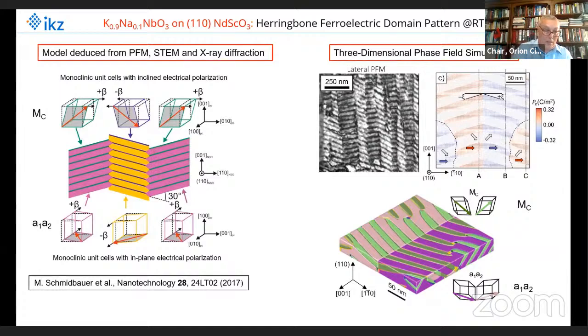On the other hand, when you turn this unit cell by 90 degrees such that the polarization vector lies now in plane, we end up with the A1, A2 phase. And you see now that the herringbone pattern is composed of a regular arrangement of these MC and A1, A2 phases. And you see this already also at the right side with the lateral piezo response force micrograph.